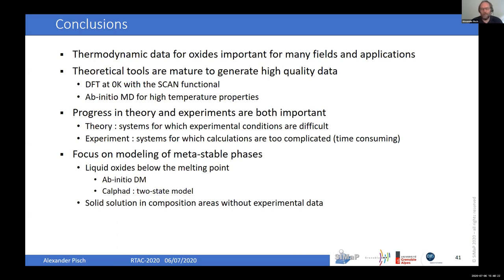And then when you add lattice dynamics, you can have properties at higher temperature. And when it comes to very high temperature, ab initio molecular dynamics really gives you interesting results, with the drawback that computers are still not fast enough to get the results quickly. So you still have to wait for a week or sometimes a month to get a result. But things will improve in the future, and I think this can then be a good way of generating new data.